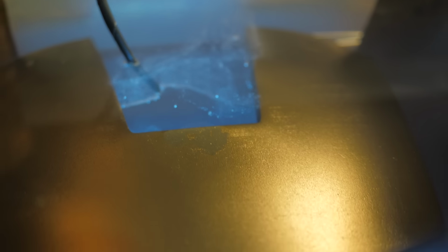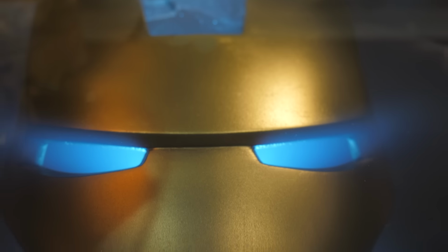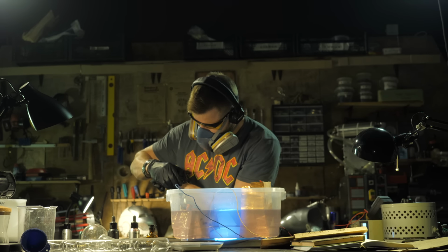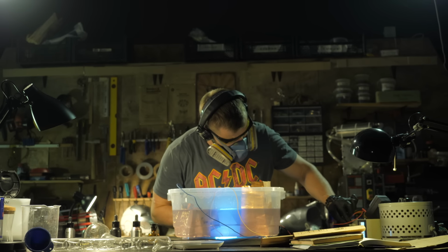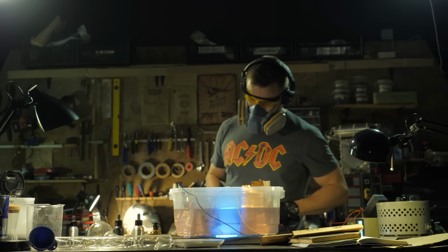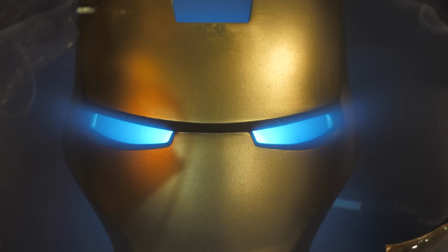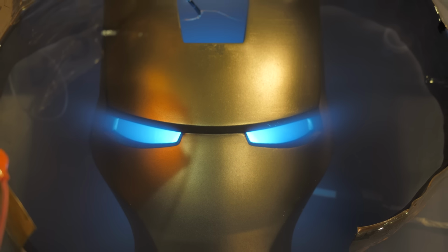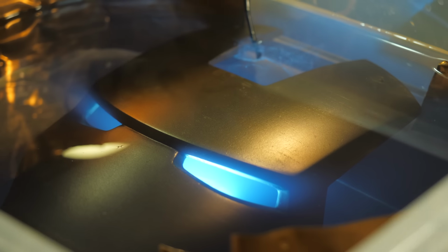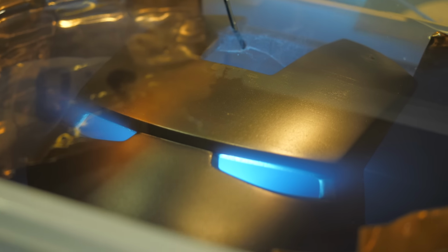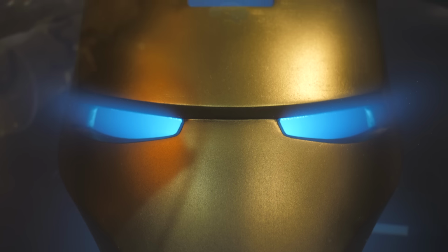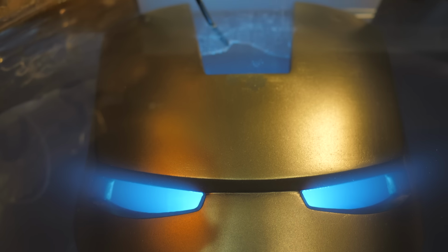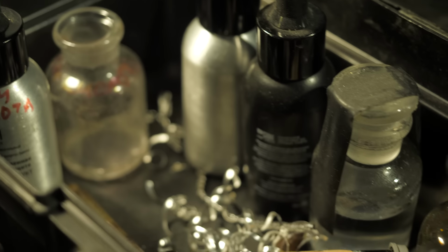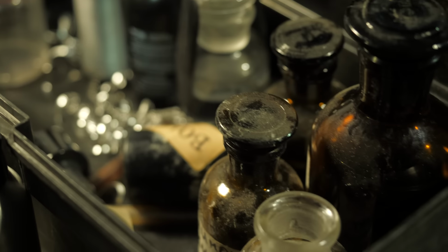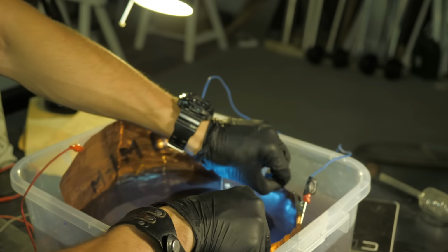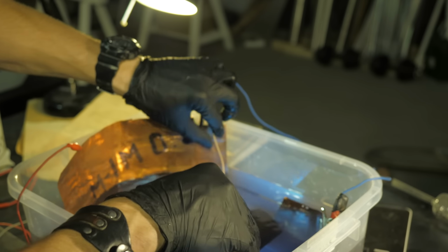But even after a week of experiments, this process still looks more like magic than science to me. Just imagine, even a 1 degree change in the electrolyte temperature affects the shade of the copper layer. Not a DIY slime making, right? After copper plating, washing, neutralizing and building up the copper layer, nickel and chrome plating can also be done. This requires even more difficult to obtain chemistry, constant control of the elevated bath temperature, and most likely knowledge of spells, mandrake juice or unicorn blood.